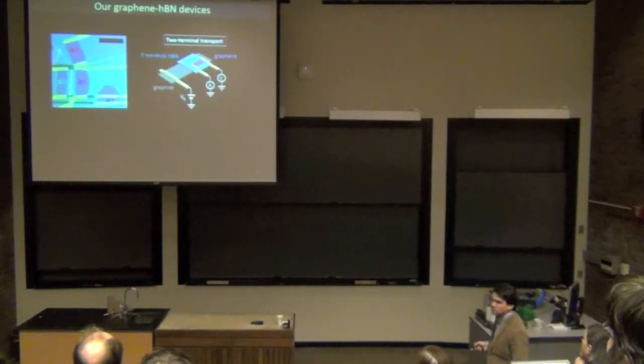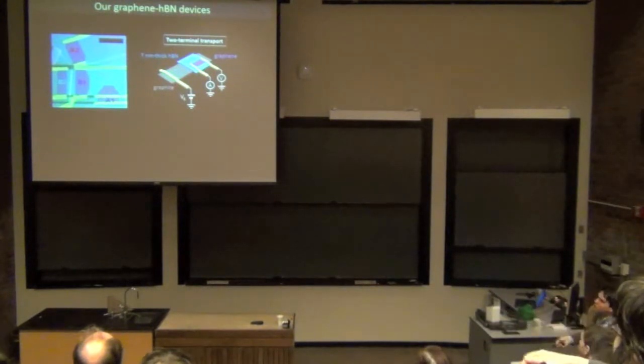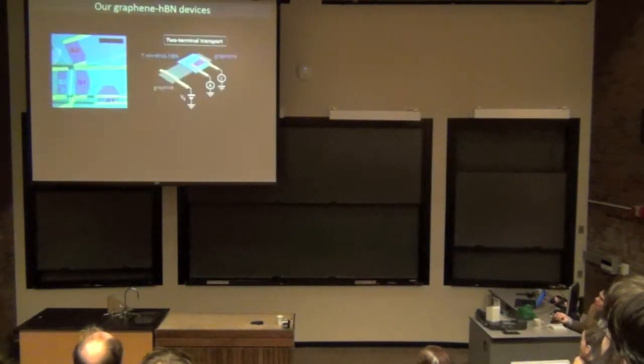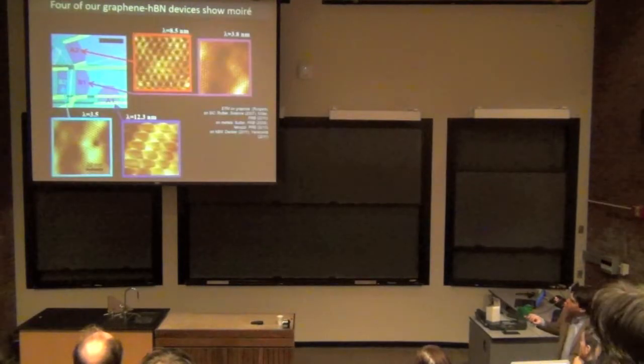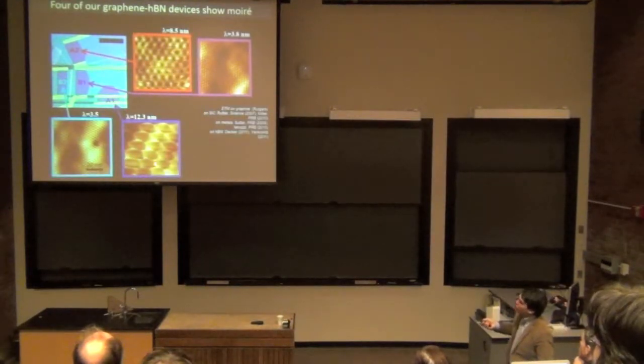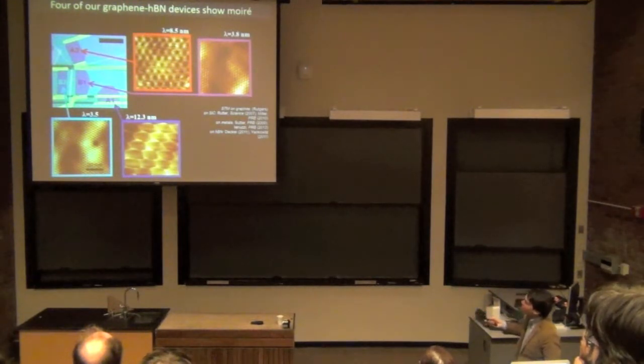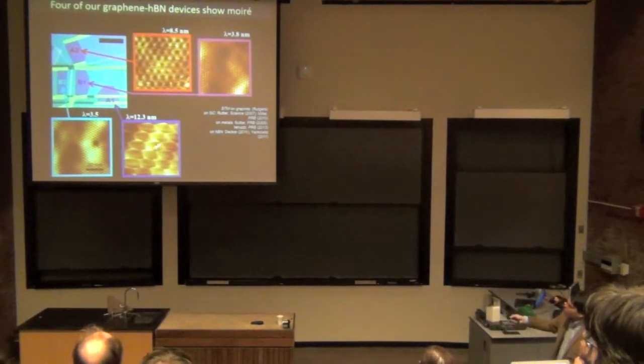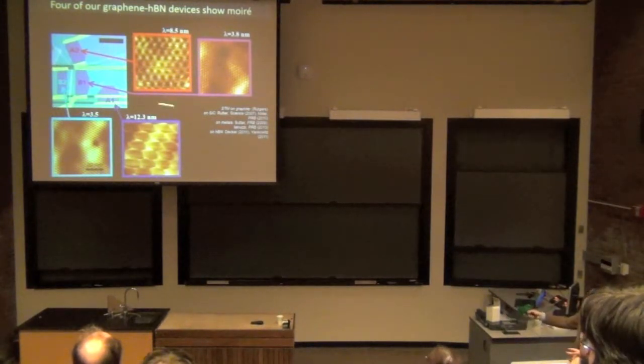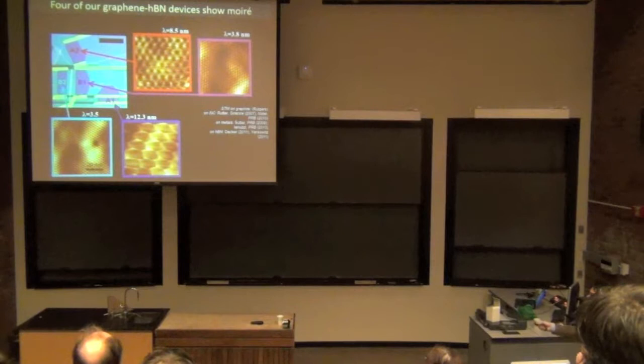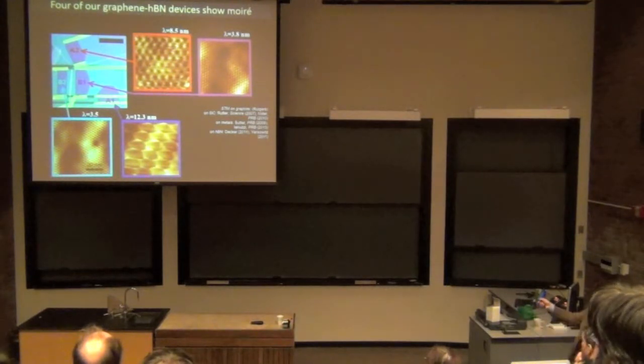So we made devices in this field effect transistor configuration. And in fact, of these four devices that we studied, all of these showed moiré patterns. These are now STM images of each of these devices that we made. You can see that this periodic moiré pattern varies from 3.5 nanometers in this picture to up to 12.3 nanometers in this picture. And this is close to the theoretical maximum of 14 nanometers that I showed on the animation slide.